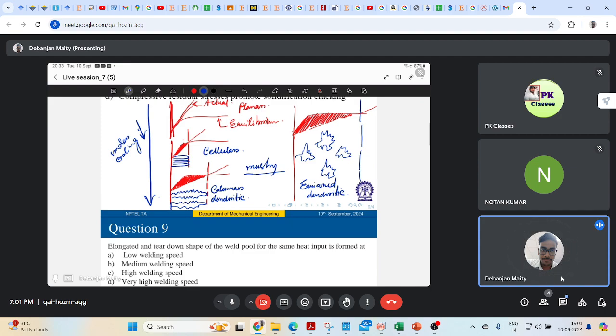So you are widening this TL minus TS, and you are widening this supercooling, there will be more tendency to form an equiaxed dendritic structure rather than stretching it as a columnar kind of structure. There are different theories to explain this in an analytical or semi-empirical or empirical form. Yeah, fine. So is this good enough?